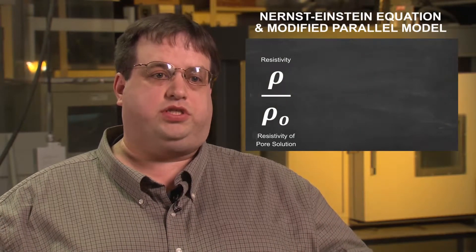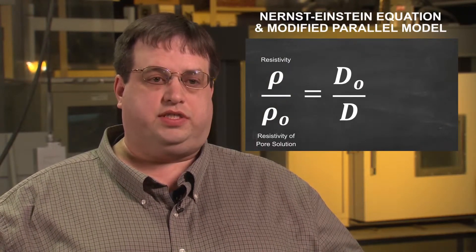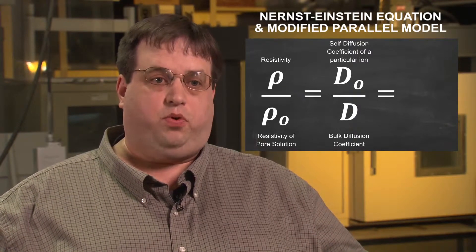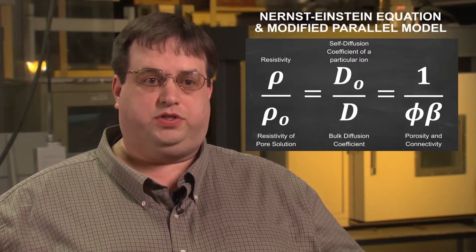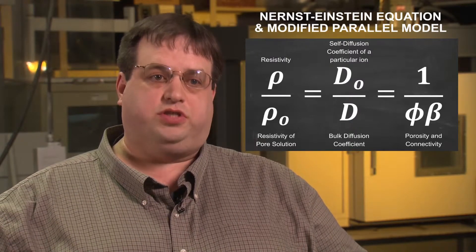The resistivity test itself is very fundamentally based in science. We can use something called the Nernst-Einstein equation to directly relate the speed at which the ions are moving through the concrete to the electrical resistivity, when we account for the properties of the pore solution and the speed of the ion itself in an open solution.